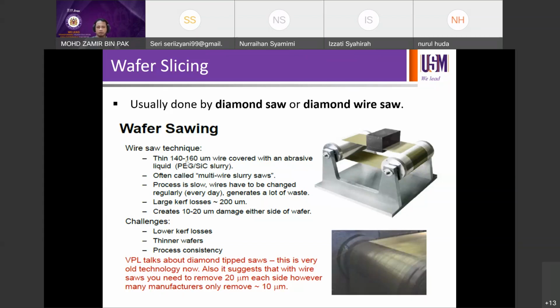this is actually the diameter of the wire, 140 to 160 micron, covered with an abrasive liquid. Abrasive is like rough particles that you can use around the wires in order to enhance the cutting process and increase its efficiency. Its effect is more or less like sandpaper. When you use sandpaper, you can feel the roughness of the surface, isn't it? So that roughness is transferred to the wire saw process, the diamond wire saw.